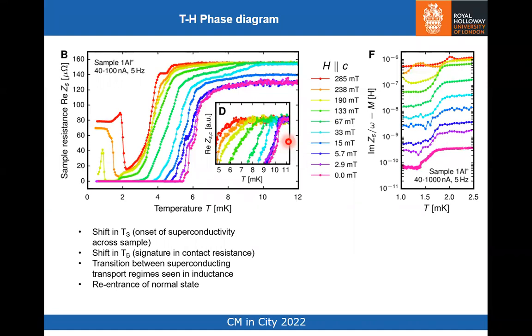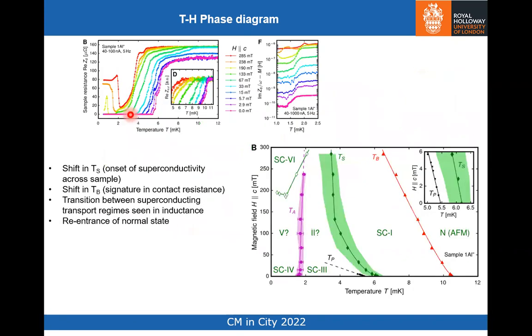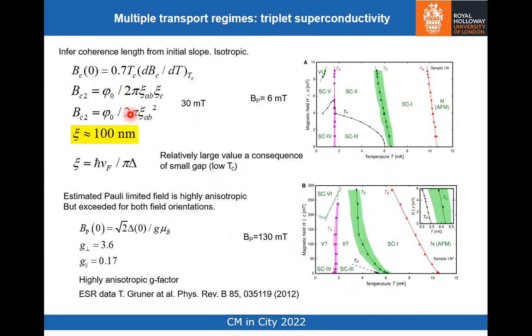Now we do the same thing for fields parallel to the z-axis, and you see similar signatures, qualitatively at least, in the shift in all of these various transitions. You also see re-entrance of the normal state, and so that's summarized then on this phase diagram. So what we better do is compare the two field orientations.